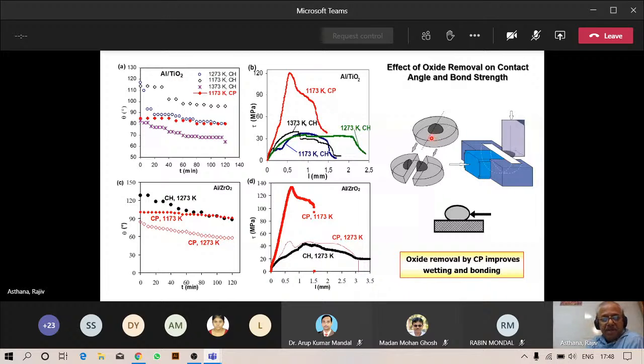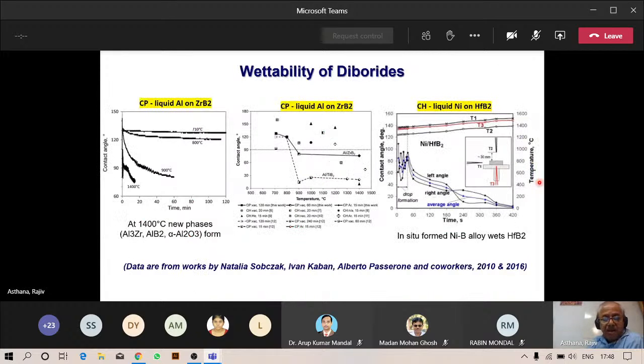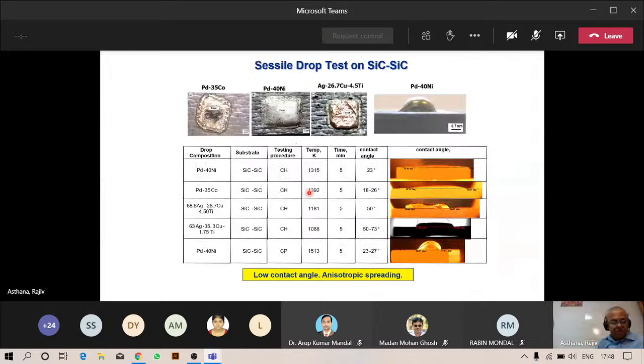This kind of a wettability test has been done on other ceramics, high temperature or ultra high temperature ceramics like zirconium diboride or hafnium diboride. And again, you would see the same kind of behavior with contact heating versus capillary purification. We did some work for composite materials, wetting tests on silicon carbide composites. And even though our contact angle measurements are not thermodynamic contact angles, they are practical usable contact angles.